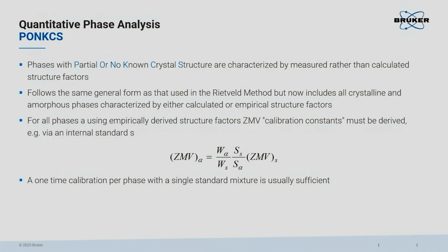The PONKCS method entirely relies on the Rietveld method. However, the ZMV factor, where Z is the number of formula units in your unit cell, M is the mass of your unit cell, and V is the volume of your unit cell, which in the Rietveld method is of course obtained from your crystal structure, will be replaced by measured ZMV values. So you can quantify phases of which you do not know the crystal structure partially or at all.